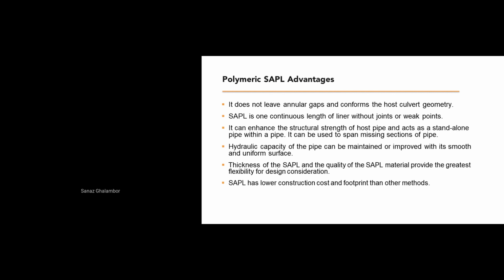Polymeric SAPL is applied directly on the substrate, so it doesn't leave any annular space, annular gap between the new polymeric pipe and the host pipe. It is seamless, jointless. It can enhance the structural strength of the host pipe. It can maintain or improve the hydraulic flow capacity of the pipe, and the thickness and quality of the SAPL material can provide the greatest flexibility for design because the system is not prefabricated. So we are not inserting a new pipe inside the pipe. We are spraying a new pipe inside the pipe. So we can continue spraying layers and layers until we get the required thickness. That makes the whole thing much easier for us.